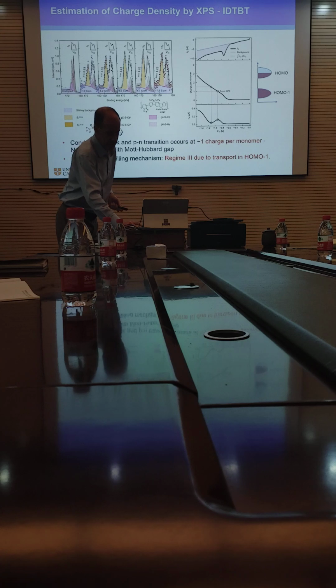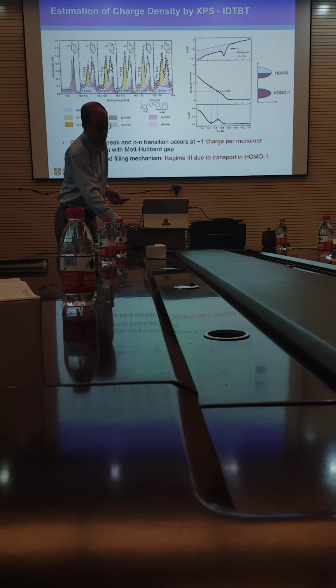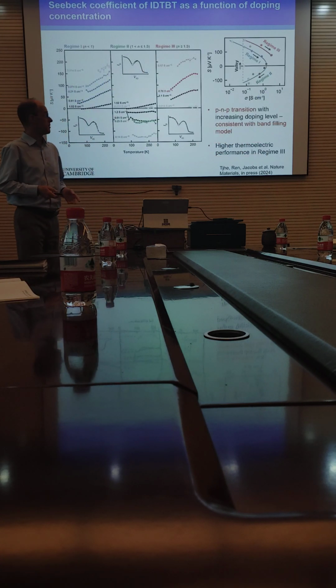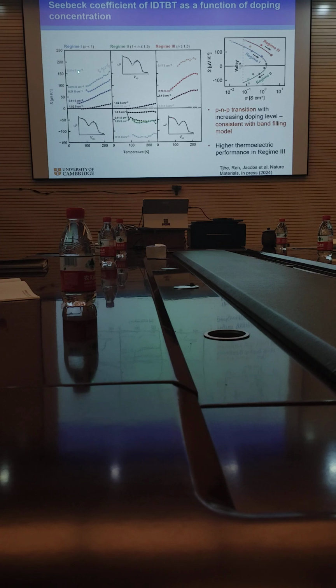And that simple band filling interpretation is in fact consistent with the Seebeck coefficient. What we see in the Seebeck coefficient, in regime 1, the first regime where we increase the conductivity towards the peak, is the p-type Seebeck coefficient decreasing as we approach the peak. At the peak itself, the Seebeck coefficient switches from p to n and becomes negative. And then if we push even further into regime 3, the Seebeck coefficient jumps again and becomes positive.